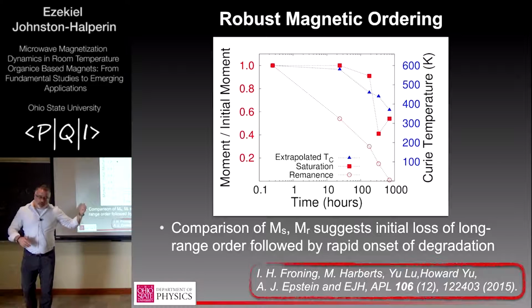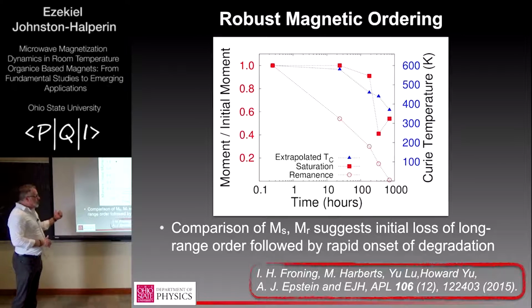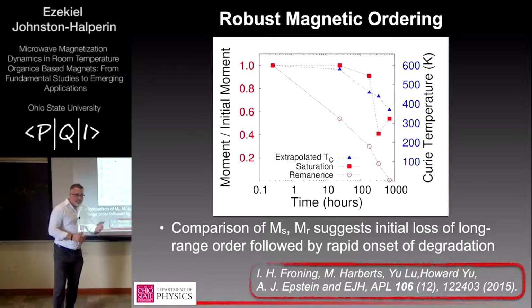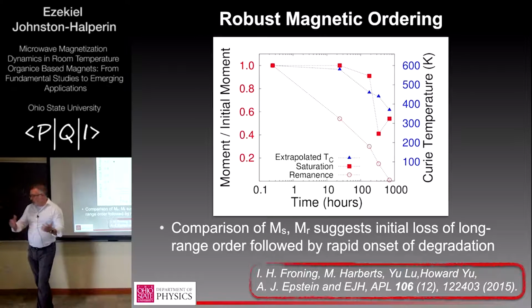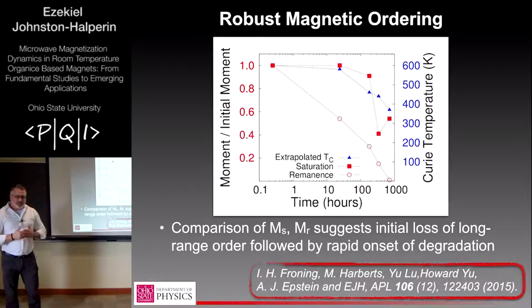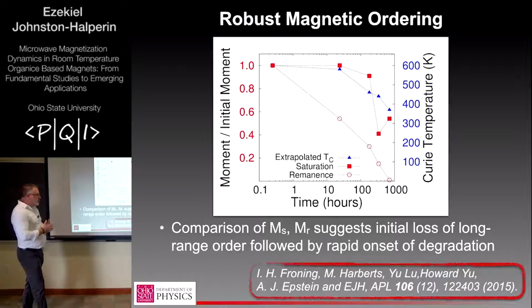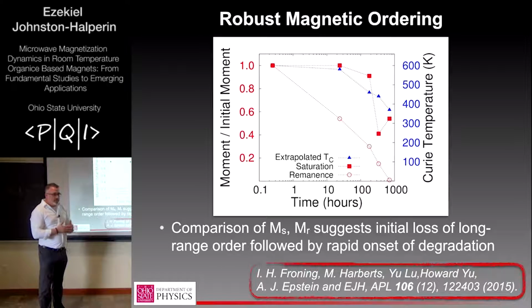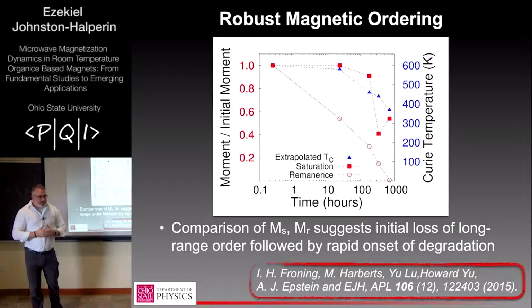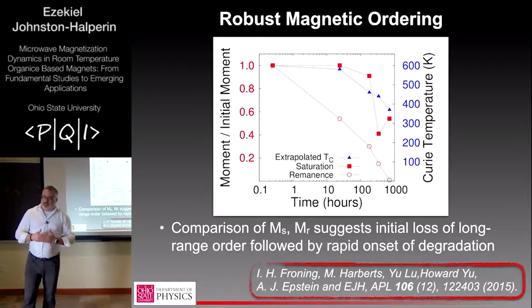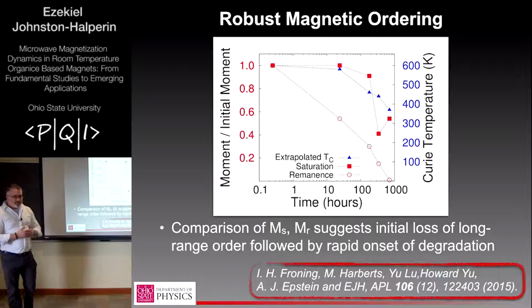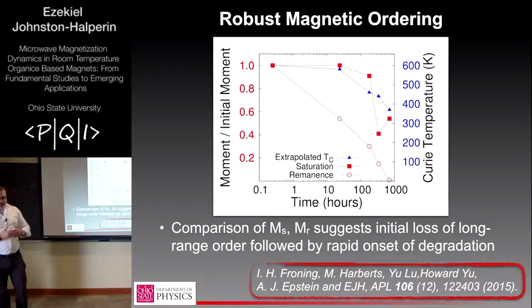We have unpublished data with thick FMR films showing that they were good, I guess, for similar time scales. So are these just left in air? Yep. I see. But if you keep them in a dry nitrogen environment? Yeah, if you keep them in a glove box, they last much longer. And if you keep them cold, they last forever.